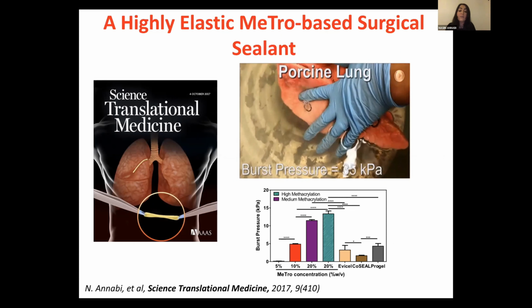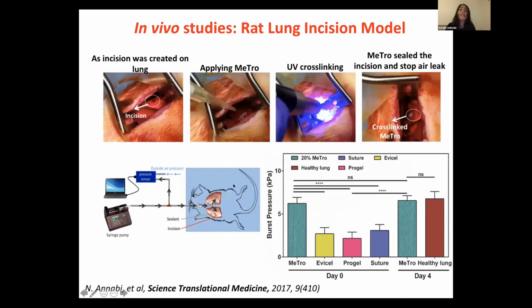So our goal was to improve Metro properties in a way that we can achieve higher burst pressure and better adhesive properties to the tissue once we apply it. When we developed this biomaterial, which was published in Science Translational Medicine, we did extensive characterization to find the right formulation. Then we applied it in different models. And as I mentioned, we always start with a small animal model. So this work was in collaboration with a medical doctor at Harvard. And then to test this material in rats, they formed a defect on the lung of the rat with a biopsy punch. We deliver our Metro as a liquid on the defect site.